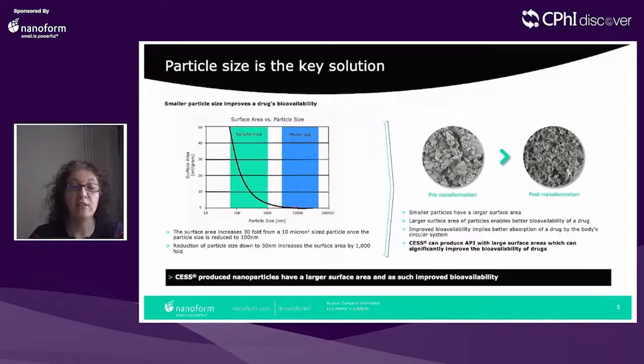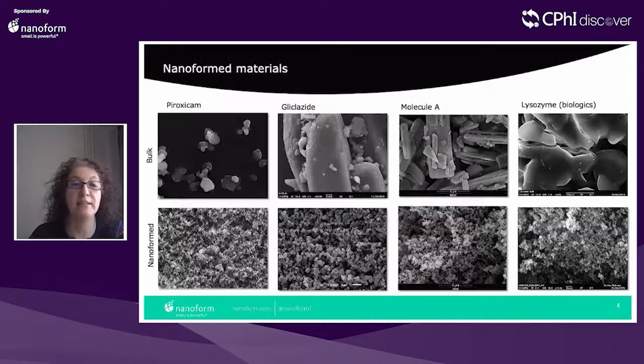As can be seen in the plot on the left-hand side of the slide, reducing the size of the particles from 10 microns to something like 100 nanometers increases the surface area by 30 times. And this goes up to something like 1,000 times if we go down to 50 nanometers. So smaller size means a much higher surface area available, which means that the drug is much more accessible. You can see how a nanoform drug looks on the right-hand side of the slide. We have small homogeneous nanoparticles, and this means improved bioavailability. So reducing particle size is the key to improving bioavailability.